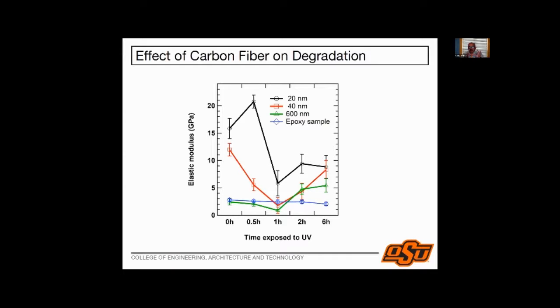So this is a snapshot of the degradation of a polymer in the presence of a carbon fiber as a function of time as you go further and further away from the carbon fiber. We find that the presence of the carbon fiber affects not only your starting modulus, which at time t equal to 0 is your starting modulus, but also exactly how this modulus changes as a function of time. So in order to understand degradation in these materials, not only do you have to know that the presence of the carbon fiber is affecting the degradation of the material when we expose it to UV, but it is also affecting it depending on how far or how close we are.